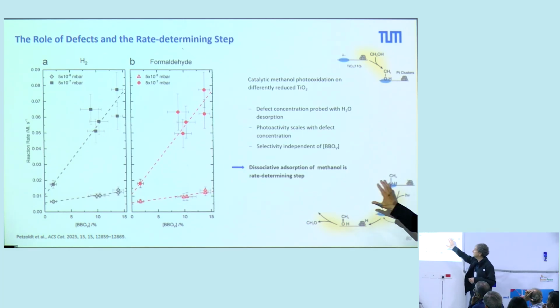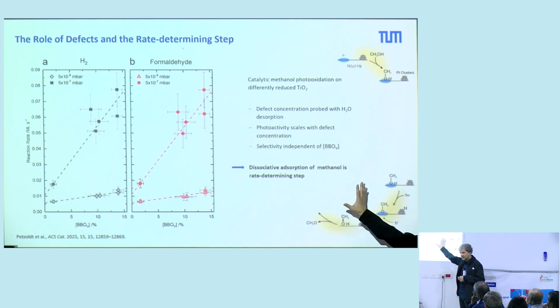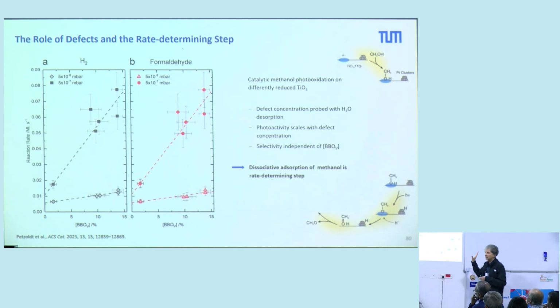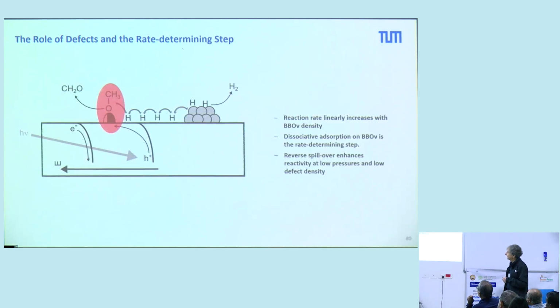That means this dissociative adsorption of methanol is the rate determining step. This is the key, that you adsorb this on these BBO sites, you make the methoxy or the alkoxy. So this is a very important step. That means, here again shown here, this is the rate determining step. And then we need the holes to oxidize this to the aldehyde.